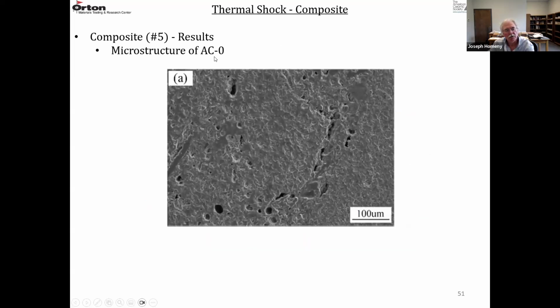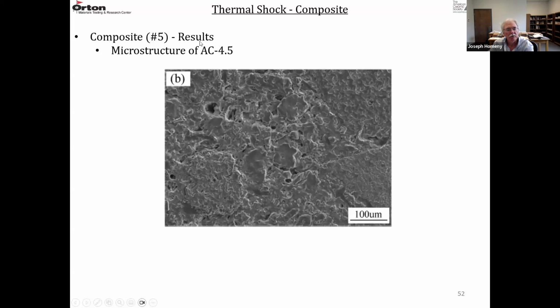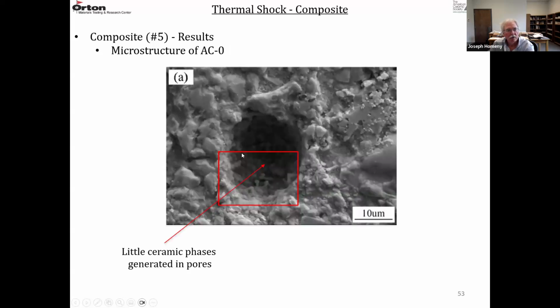So this is the microstructure of the material without any composite powders. There's not much to see here. It's pretty dense as formed, and you can see some black spots, some porosity. And this is the microstructure of the material with 4.5% graphene carbon spinel additions. There's some porosity present. So if you look at the microstructure here, this is the material AC0, no composite powder additions. You can see one of the pores here.